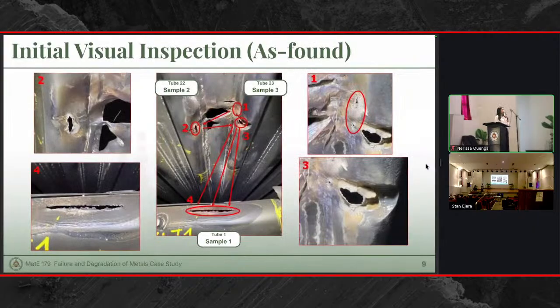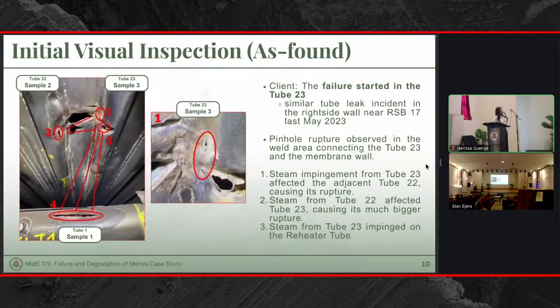Upon closer inspection, we can see that sample 3 has two smaller holes, which are the pinhole rupture and the smaller elongated rupture above, and then it had one big hole, and sample 2 had one rupture, and sample 1 had one rupture as well. So the client was also able to provide an initial report on the sequence of events for the failure, and from the report, the failure started from sample 3, from the pinhole rupture, and the pinhole rupture caused steam to impinge on sample 2, which then caused steam impingement again onto sample 3, causing the bigger rupture to occur. And then the steam impingement from sample 3 impinged on sample 1, which caused its failure.